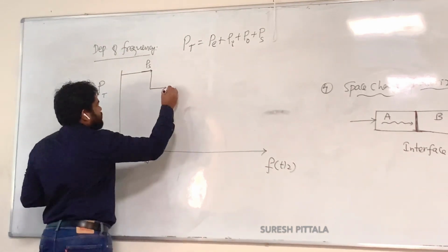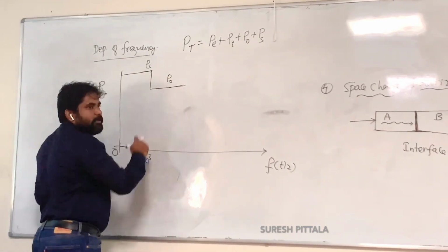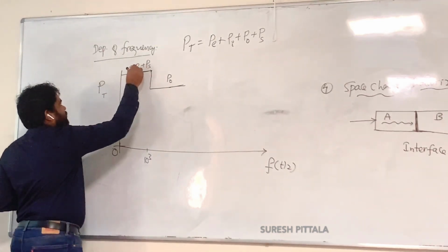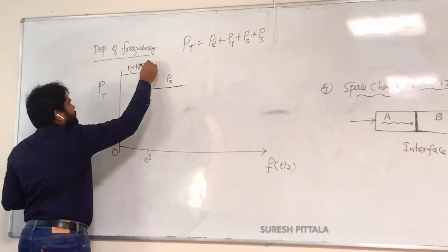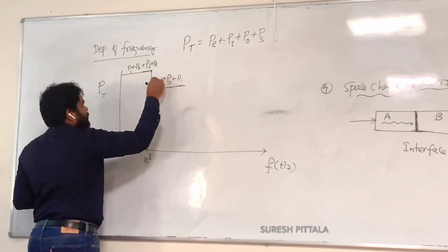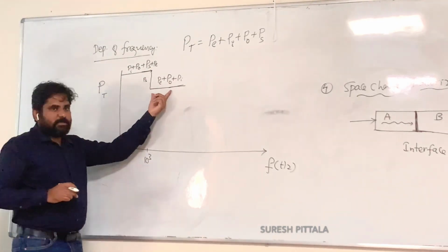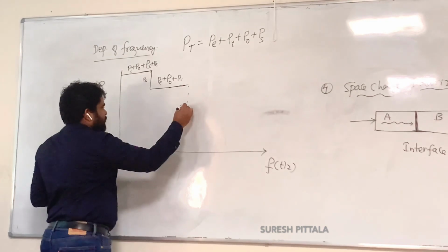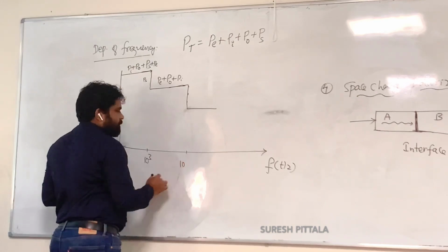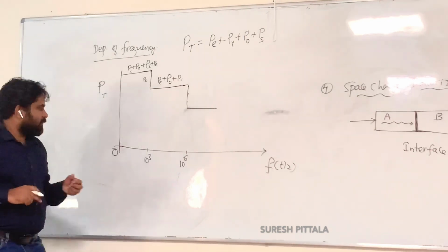Then, which one will get dropped off? Space charge. PS will get dropped. So here we have all PS plus PO plus PA plus PE. But here you have only PO plus PA plus PE. So in between you lost the PS component. Only these three will be there till 10 power, infrared range, I need to look at the notebook, but let's say till 10 power 6.